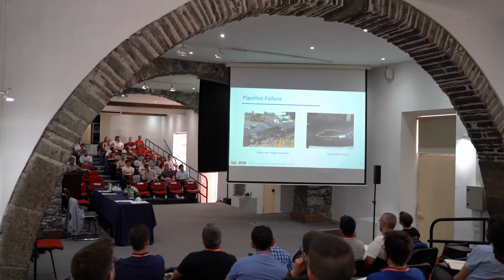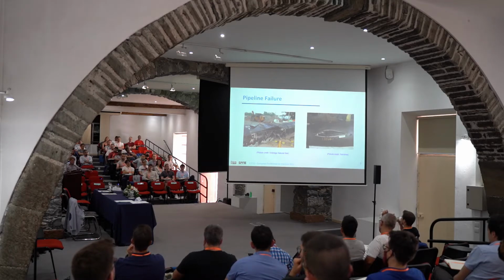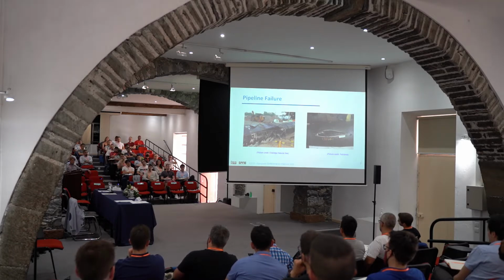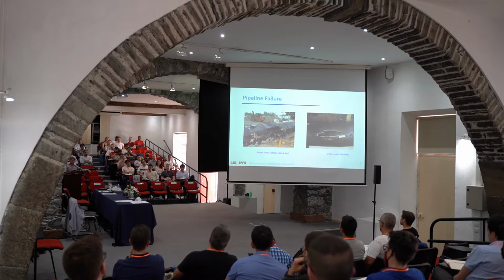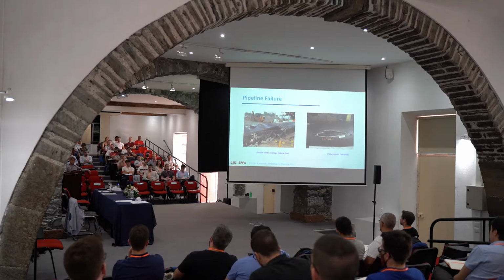And very common also is pipeline failure. Here in Europe, especially in the US and in Canada, the US alone has 500,000 kilometers of pipelines. And it's a very common failure actually. We don't hear a lot about this, but usually it's ductile at the end, but in most cases it begins as a very small cleavage cracking, either by stress corrosion cracking, or even corrosion, localized corrosion, pitting corrosion, that eventually will evolve into a microscopic crack.